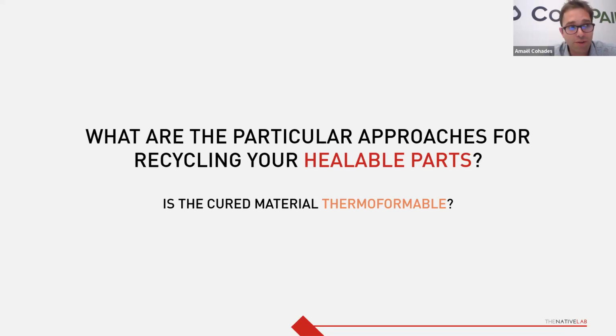But those materials typically have a Tg of 140 degrees minimum, so we are healing below. That's the most important thing: to keep the structural properties of the materials during healing. If we play well with the temperatures, then we can bring this thermoformability on specific thicknesses. For some applications produced on the press, we have seen this as a really interesting outcome: bringing already cured materials to them for just pressing, and then you are done. This is also really interesting for mass volume markets, where you do it and then go to the next step.